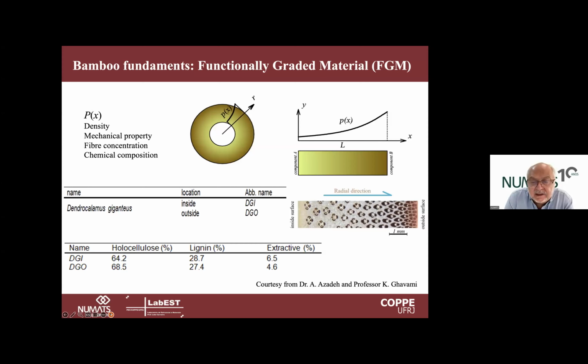So just starting, bamboo is a functionally graded material. Normally, when we take the strips of bamboo closer to the outer side, we take it from a part where it has higher mechanical properties because it has higher fiber concentration, also has more holocellulose. The density is higher in the outer part of the bamboo. So bamboo is a naturally functionally graded material.